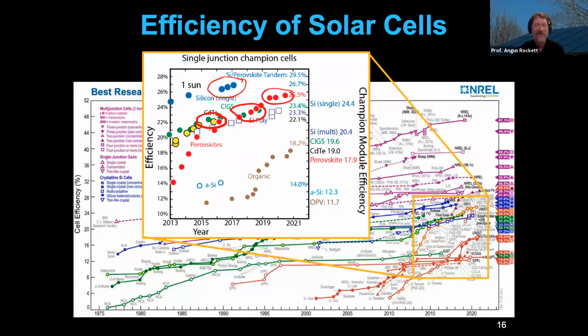Well, that depends on what the energy gap of the perovskite is. If you can make a perovskite with a 1.4, 1.45 eV energy gap, then you'll probably hit a potential of something like 37% efficiency in 1 junction. Gallium arsenide is about that same energy gap, and it has only achieved about 27% efficiency. So I think it will be difficult to keep pushing these perovskites higher than 26, but if you can make them stable, a 26% efficient solar cell that you combine with a silicon solar cell, you can make a 1.7 eV gap cell at 26% efficiency routinely and stack it with a silicon cell routinely. I don't think you'll have any problem until somebody comes along and figures out how to make a triple junction or something.